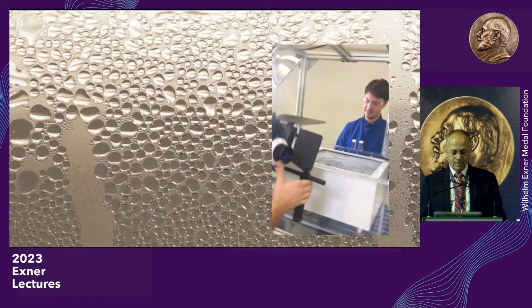And later we tested the water, and it's completely pure. It has no metals, no organics. So in fact, it's cleaner than any water you could ever find. It's absolutely pure. The material is very stable in water, so the metals and organics don't leach, and the MOF itself, because of the pore size, is a molecular filter. In fact, this is distilled water. So for it to have a nice taste, you need to mineralize it, which is something that could be done easily.